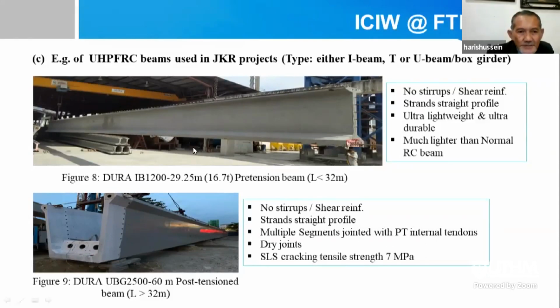Figure 8 shows one example of an I-beam of 1.2 m height, 29.25 meters long. And Figure 9 shows the U-beam, 2.5 m height. Compared to normal concrete, where we definitely use reinforcements, for these beams we do not use reinforcement, but only fibers. Therefore, no stirrups and shear reinforcement are required. Multiple segments can be joined with internal PT tension, and we only use dry joints. And the SLS cracking tensile stress is 7 MPa.